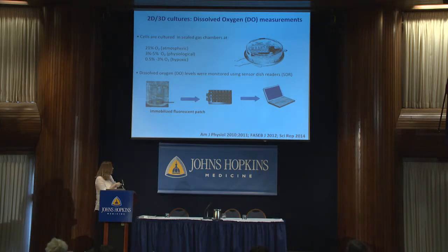What we found, in a series of studies, is that the cells by themselves consume oxygen. So if you think you flushed 1% oxygen and this is what the cells see for 72 hours, this is incorrect, because the cells keep consuming oxygen, they're getting very low oxygen supply, so very quickly what is in these petri dishes is very anoxic conditions.